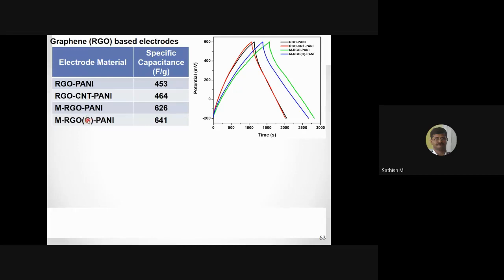Here we use graphite instead of carbon nanofiber. Otherwise, these two samples are the same preparation. This sample shows 600 plus farad per gram, whereas the conventional one shows only 400. It's almost 50% increment in the energy storage.